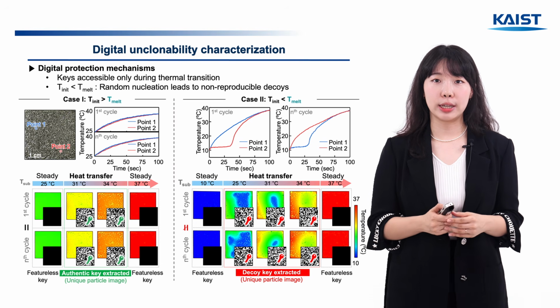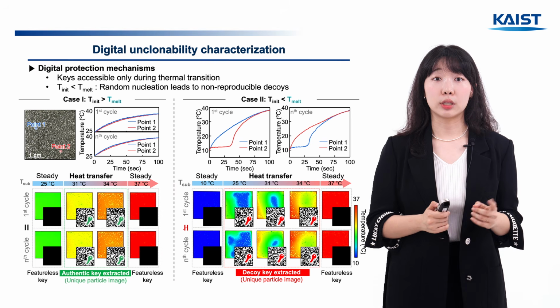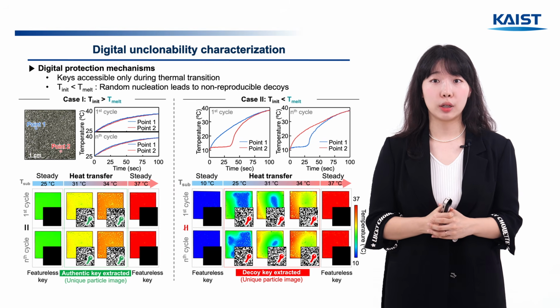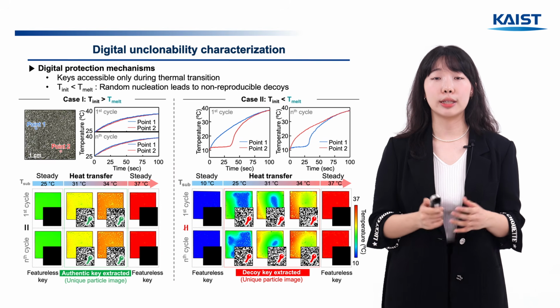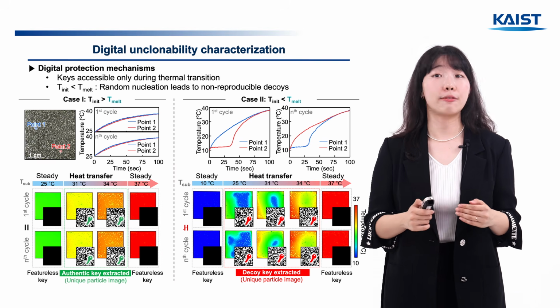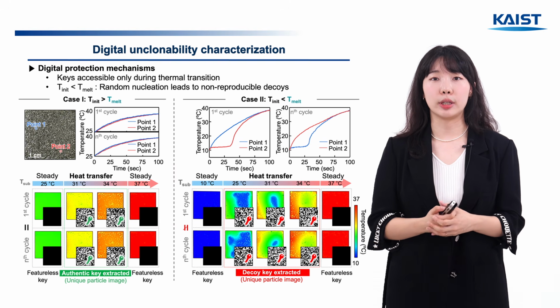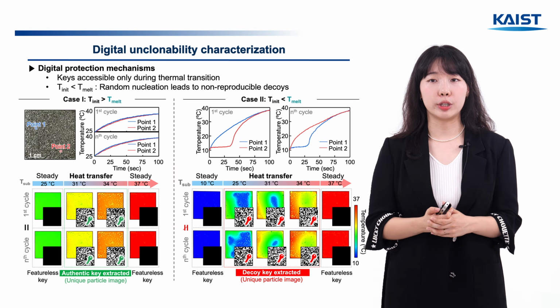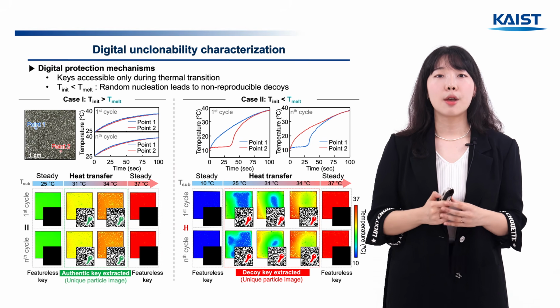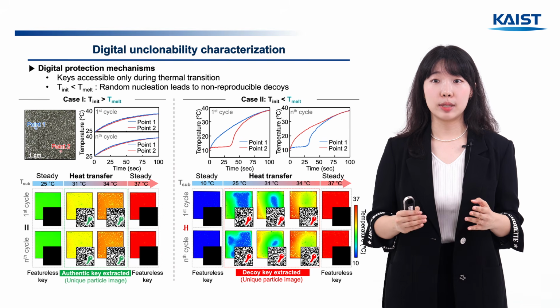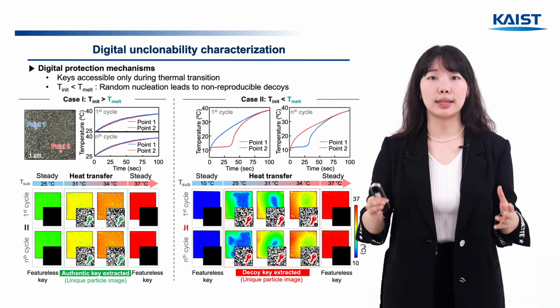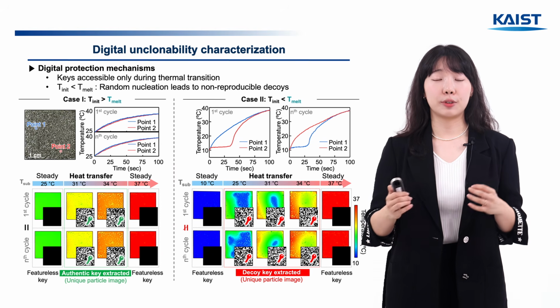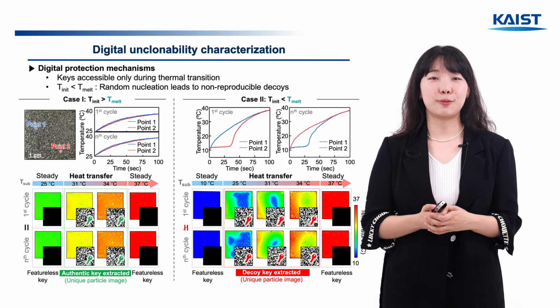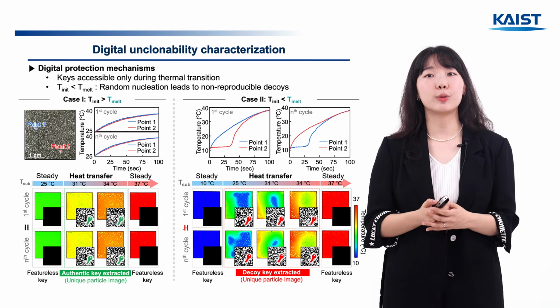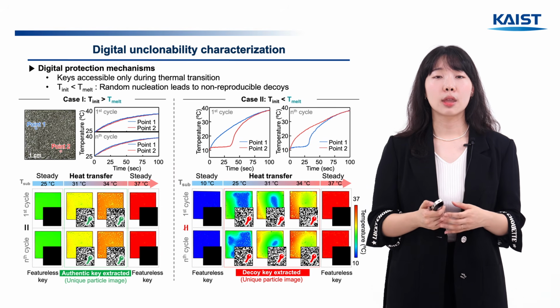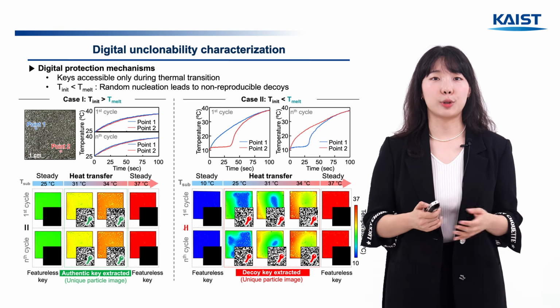And let me explain why the key changes depending on the starting temperature. First, when the starting temperature is above the melting point, all the particles in the PUF rise in temperature in the liquid state, so the heating behavior is the same every time, which generates the reproducible, real key. The case where the starting temperature is below the melting point is different. Freezing begins at random locations and times, and the particles don't freeze all together as one mass. They freeze partially and differently each time, so as a result, a different thermal pattern comes out in each cycle, producing a non-reproducible key. And that's exactly the fake key, which is used for disguise.